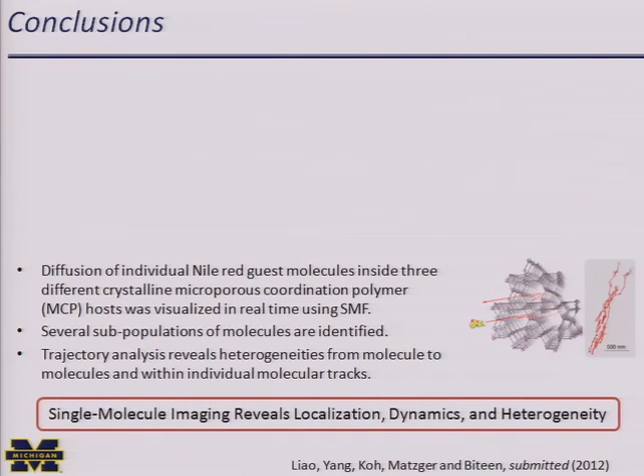So in conclusion, what we've done is looked at the diffusion of individual Nile red guest molecules inside this crystalline microporous coordination polymer host. And we looked at it in real time, and we're able to really get at the heterogeneity. There were several subpopulations of molecules. And trajectory analysis really allowed us to quantify these different modes of motion, as well as the percentages of molecules in each mode.